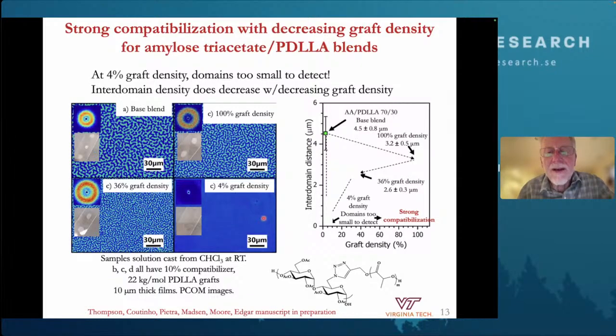And here you can see that optically, there are no phases. We have optically complete miscibility. Now, I'm not claiming that these two polymers are actually completely miscible with one another, but what I am claiming is that the size of the domains is so small that you can't see it optically anymore, and we're going to have much better properties from that material.